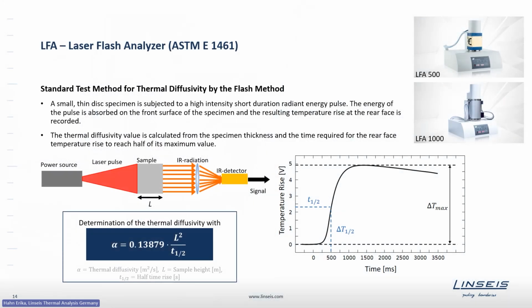We're starting from scratch. The laser flash analyzer is a standardized method according to this ASTM norm for the measurement of thermal diffusivity. This norm describes that a small, thin disk specimen is subjected to a high-intensity, short-duration radiant energy pulse. The energy of the pulse is absorbed on the front surface of the sample, and the resulting temperature rise at the rear surface is recorded, where we use an infrared detector to record the temperature rise with time. A typical signal looks like that.